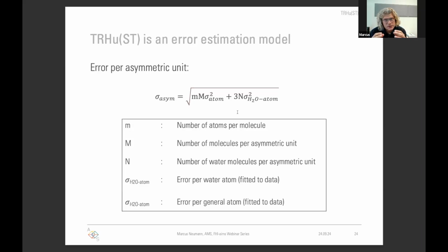And we assume that every atom in a crystal, every atom in the asymmetric unit, sees a somewhat different environment. And then over those different environments, there is error propagation for the error per atom. And we assume that error propagation is Gaussian. So we can use Gaussian error statistics to propagate our error, for instance, to the asymmetric unit of a crystal or to an energy difference between two crystal structures. And we only distinguish two atomic errors: for water atoms and for all other atoms. And those two atomic errors, we have fitted them to the experimental free energy differences in our predictions.